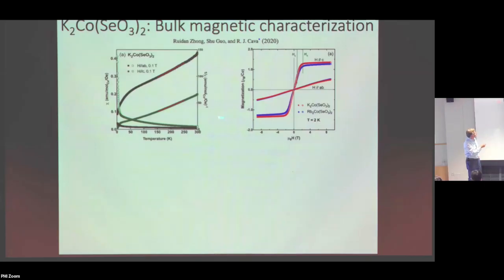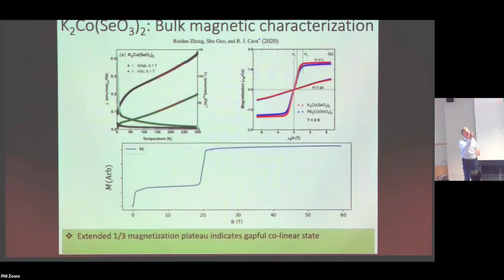So here's magnetization measurements as a function of field. And that's the first kind of surprise that came in this material: we don't come up to the full magnetization, which is a little bit more than 3 Bohr magnetons. We just get to this level. So this is kind of surprising. But that was just because there was another shoe that had to drop. We had to go to higher fields, all the way up to more than 20 Tesla, and we actually used a pulsed high field facility to come up to this other level of magnetization. This is what we call a magnetization plateau, and that's very much part of the physics of this system.